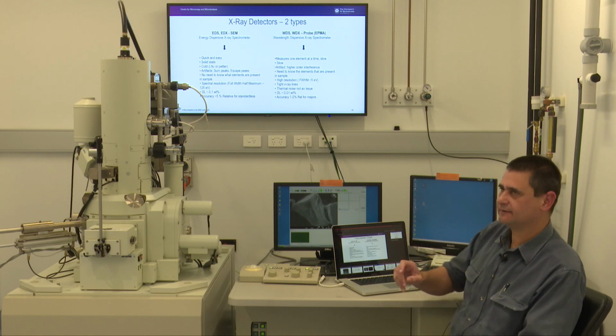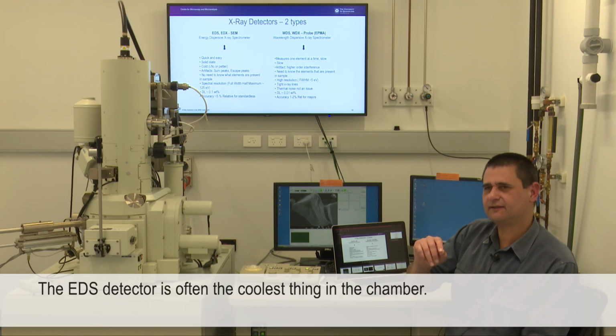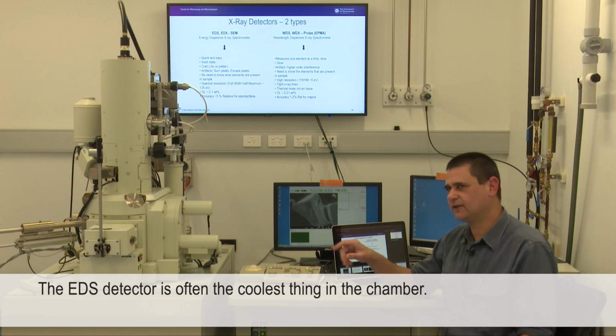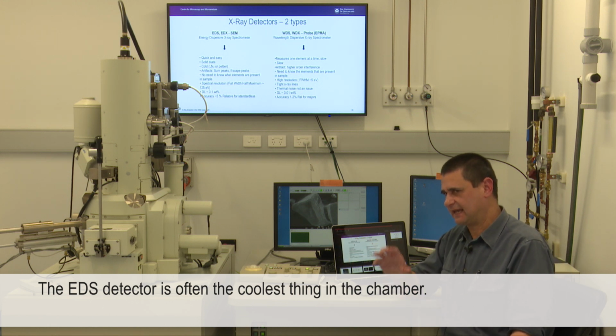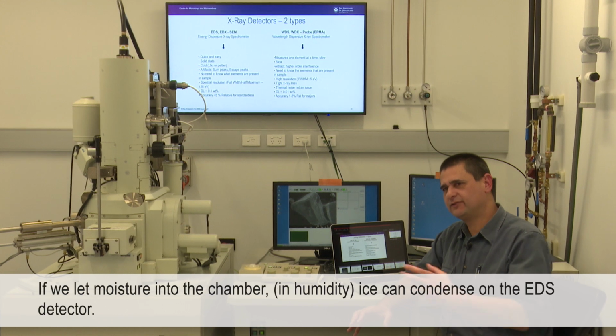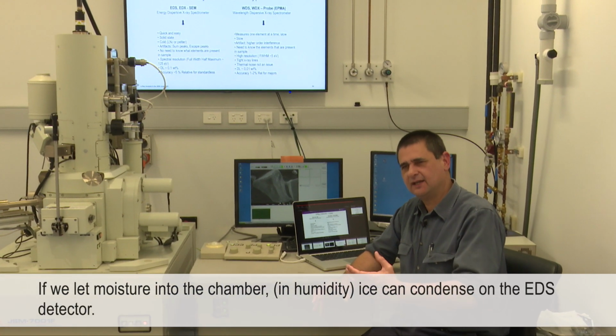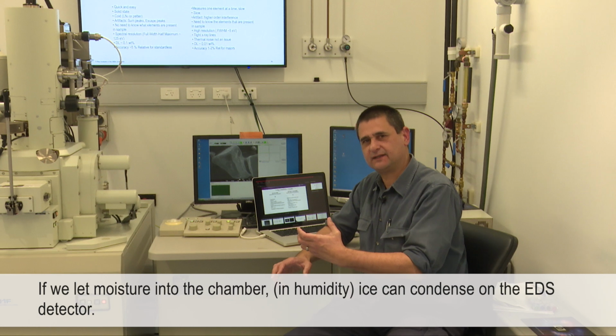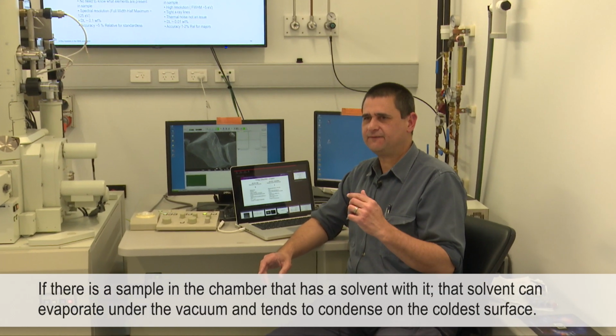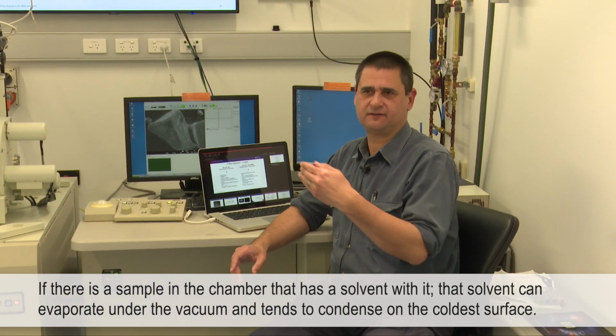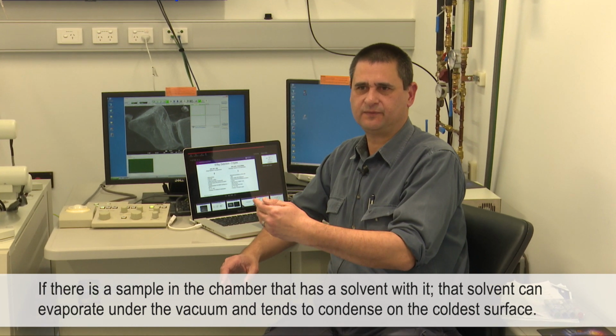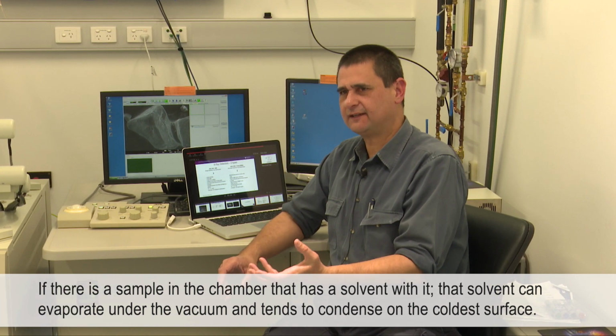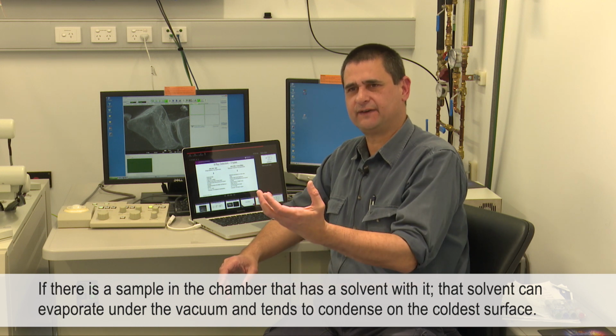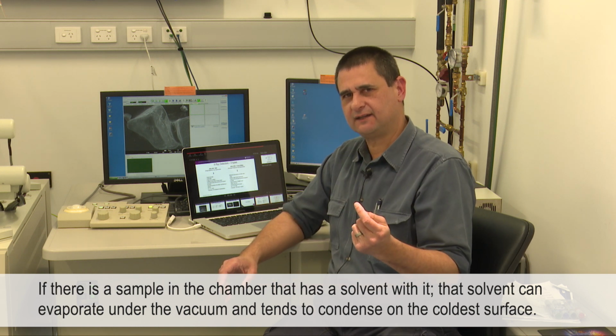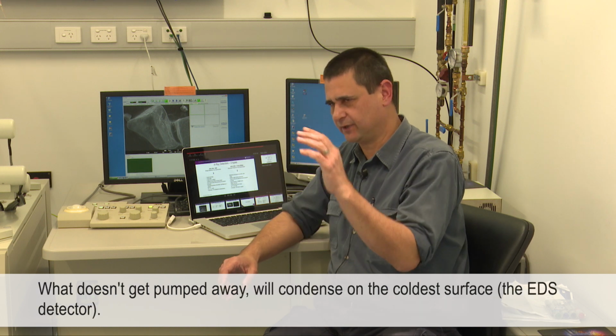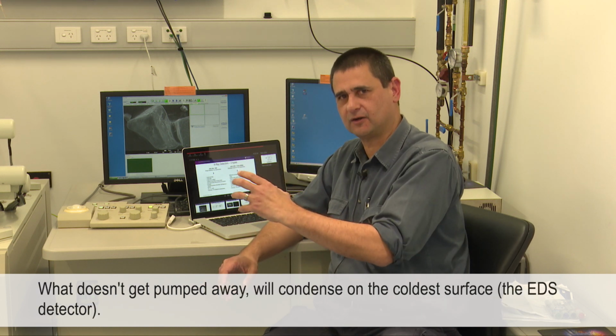I should point out that the EDS detector is cold, it's cooled. It's often the coldest thing in the chamber, and that can be a problem because if we let moisture into the chamber in humidity, ice can condense on the EDS detector. But also, if you put a specimen into the vacuum chamber that has a solvent with it, that solvent would evaporate under the vacuum, but what doesn't get pumped away will tend to condense on the coldest surface.